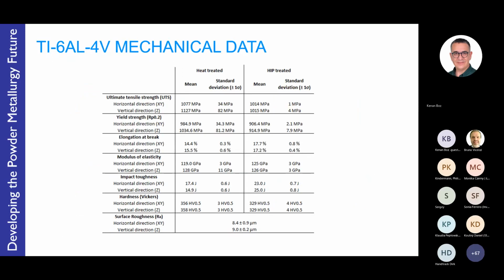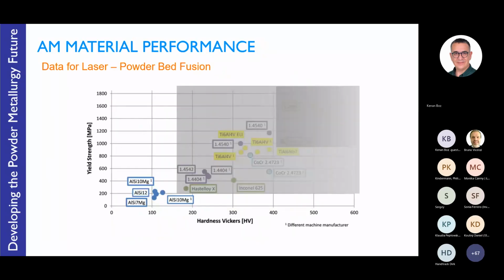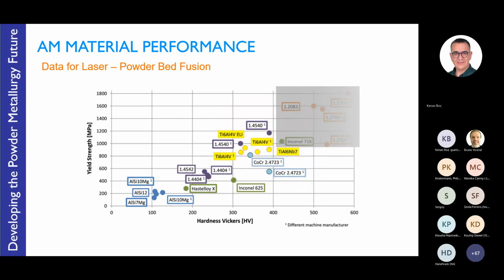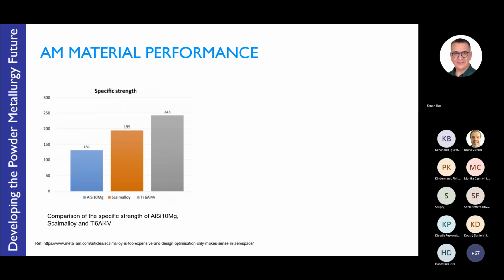And this is all available from various different sources, documenting the heat-treated and hot isostatic press material performance in terms of tensile strength, elongation, elasticity, toughness, hardness, as well as surface roughness. So there's a growing body of materials available for laser powder bed fusion, and this is an example from the EPMA. So we have the aluminium alloys, stainless steels, nickel-based alloys, cobalt, titanium, and then we have the ultra-high hard and strong maraging steels. One example comparing different materials.